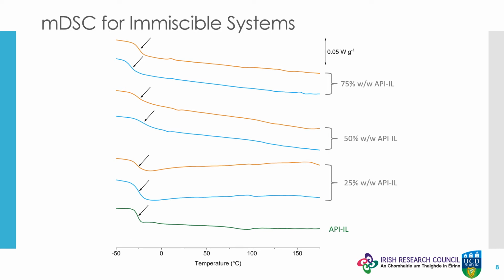Considering the conventional application of ILs as solvents, one possible explanation is that the API-IL and polymer are initially phase separated, but upon heating over the course of the DSC experiment, the API-IL is able to dissolve the polymer. As heats of solution are generally of low energy, and so likely below the limit of detection of the instrument, this would explain why no additional thermal events are observed.